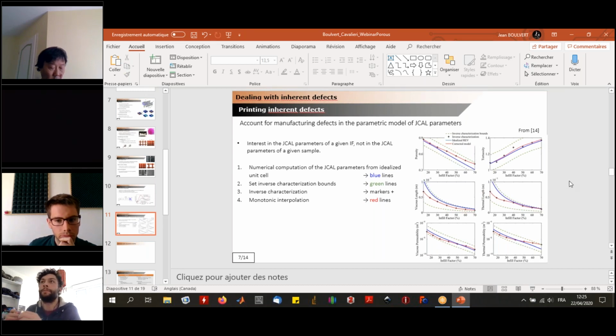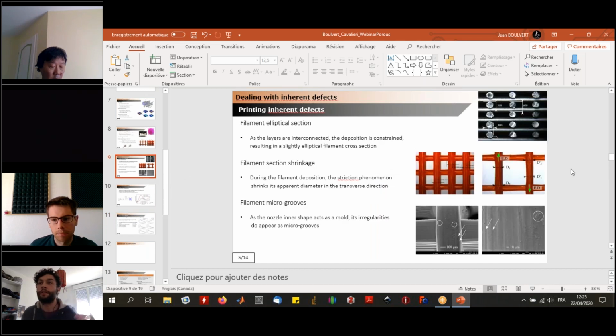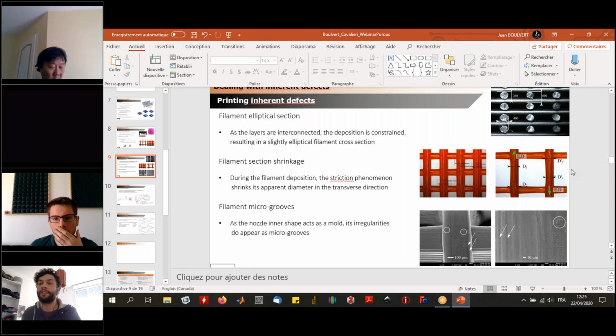So basically what we have been seeing from the homogenizations by finite elements that we have been conducting is that those microscopic defects actually completely change the fluid solid interface. And as Jean has said, since the thermal and viscous characteristic lengths are purely based on the ratio of the fluid solid interface and the fluid volume, you can actually change the thermal and viscous lengths by a factor of 2 if you have those roughnesses on your filaments, for example. So the printing defects here have a very strong impact on the lengths.